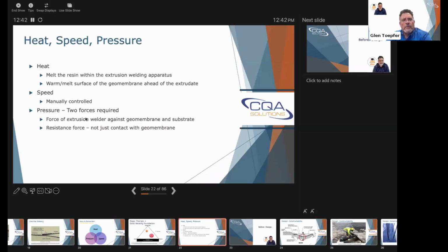And pressure, what a lot of people don't realize is there are two forces required. You have the force of the extrusion welder against the geomembrane, and a lot of specs call out that you want adequate force against the geomembrane, but you have to have that substrate below for resistance. If you have a wrinkle, the extruder can push down, but you're not getting a good bond in the wrinkle. You're not getting the resistance pressure you need, and that's something a lot of people overlook, unfortunately.